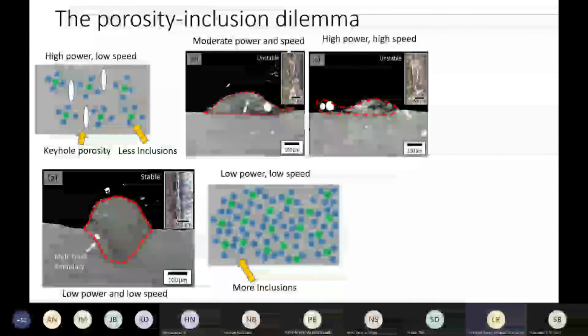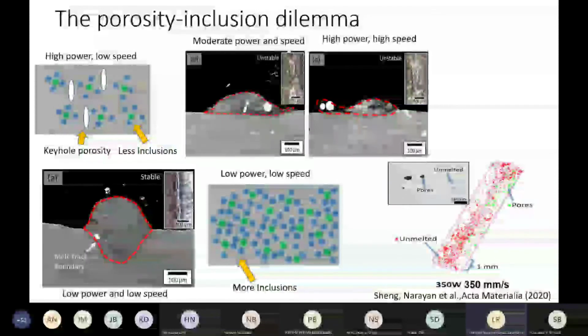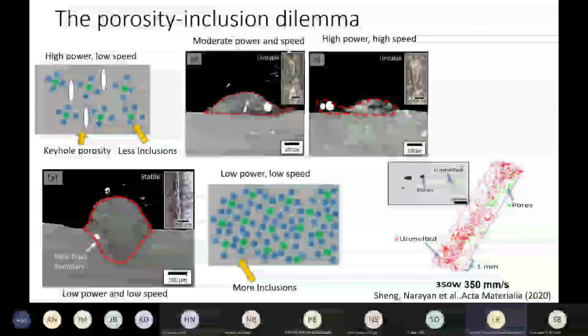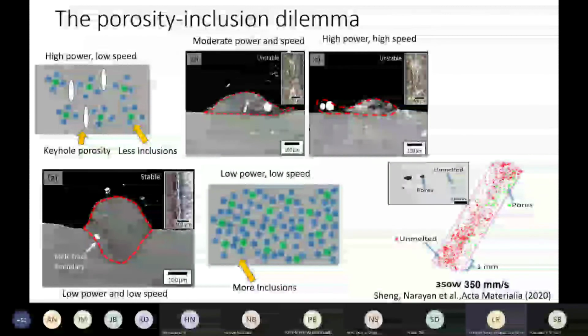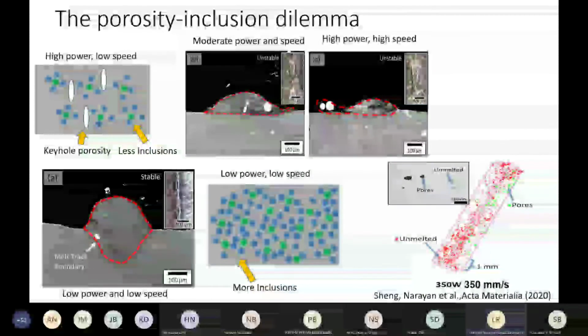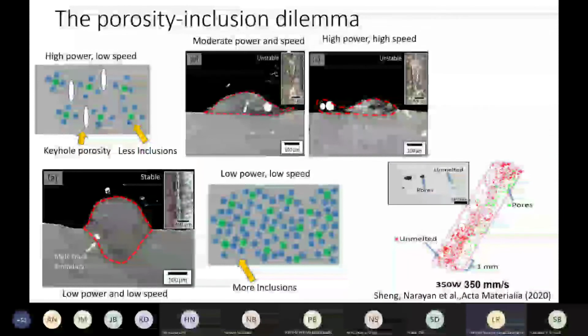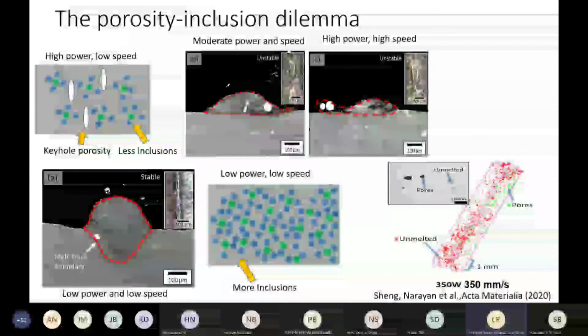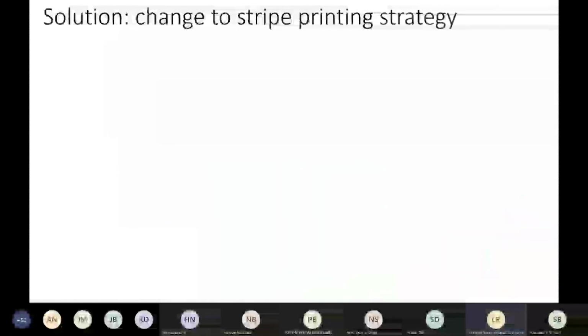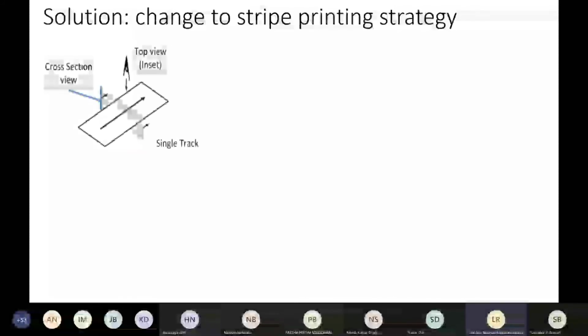So low power, low speed, although it creates such a problem, people have been living with it because it is much better than getting a keyhole porosity, which is like a hole in the material. Now what happens is this was done, and then we observed that there were several pores as well as inclusions in the material, which is what caused a lot of problems. So the solution was to change the stripe printing strategy.